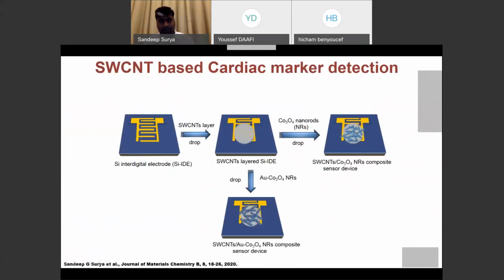Going further ahead, we have used the same approach of silicon dioxide substrate, but wherein on top of interdigitated electrodes, we have the active channel of single wall carbon nanotubes first. And then there are two more approaches of deposition. First, we deposited cobalt oxide nanorods to understand the sensitivity aspects of the sensor device. And then followed by that, we also deposited gold nanoparticle loaded cobalt oxide nanorods.